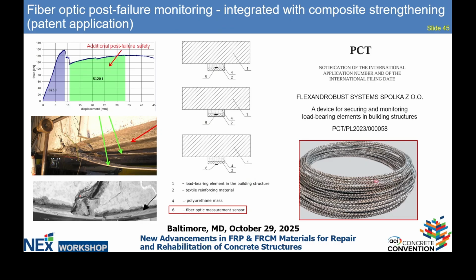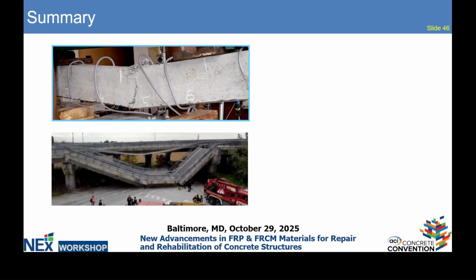Also, we can integrate the carbon fibers with a fiber optic system to measure the real life of the structure, yeah? To have information not only before the damage, but also after. So, as a summary, we propose to use this system to protect bridges that are old and corroded against damage. If you have to maintain the system, you do not have time to repair 100, 200, 1,000 bridges immediately at one time. If you bond this system, you are protected. You can hang it if there is an unexpected event.